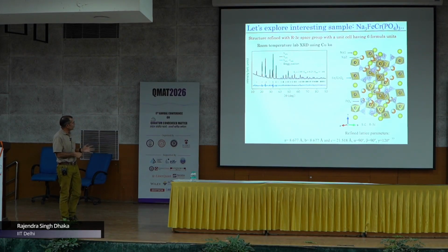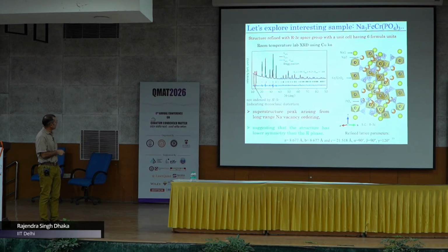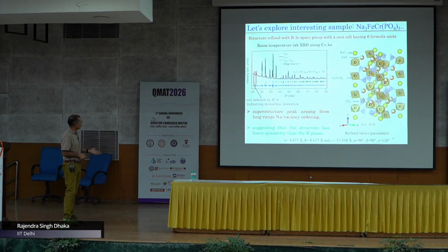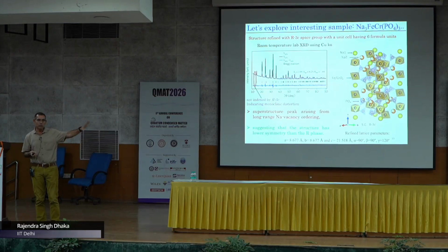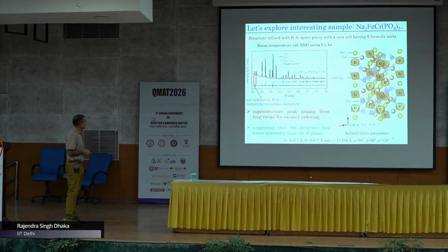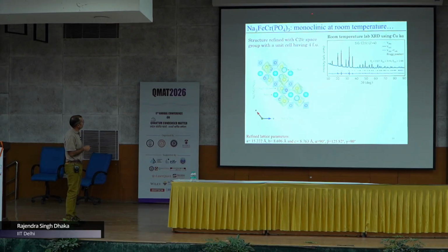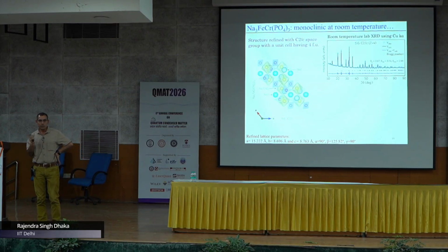Again this is the rhombohedral structure, and the Rietveld refinement could not fit a peak here. Okay, this is what is called the superstructure peak, right. So, that tells us that there is something more. This superstructure peak is coming from the sodium ion ordering. This is what we are concluding here, but of course, we cannot conclude without doing detailed analysis or detailed measurements.